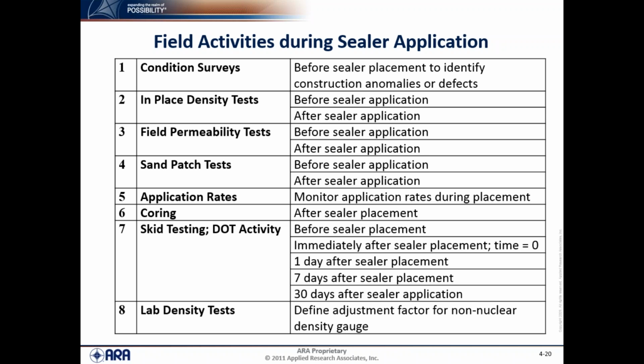We also did in-place density tests before as well as after sealer applications. Those in-place density tests were done with a PQI, a non-nuclear density gauge. We also did a water-based field permeability test both before as well as after sealer application. The sand patch test we did before and after sealer application. And then we monitored the application rates that were applied to each of the test sections.